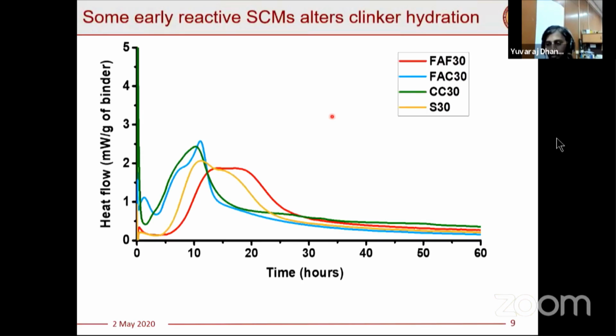So we did an experiment on a range of different SCMs. I have presented a typical result of a class F fly ash, class C fly ash, calcined clay, and slag. You can see the fly ash curve over here. But when you start adding slag to it, because slag can start reacting right from the early ages, you can see the curve is shifted to the left, which means the reactions start happening much faster.